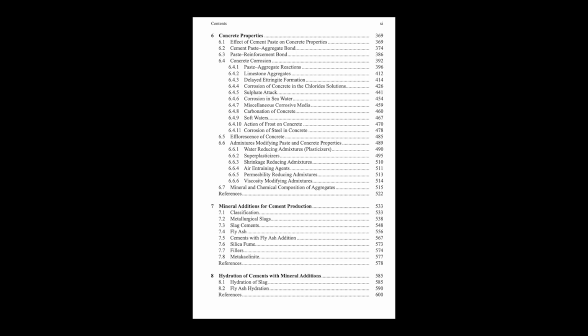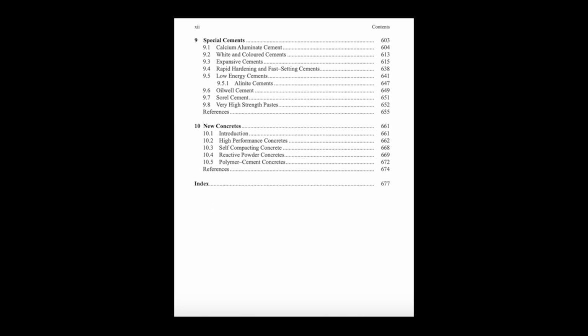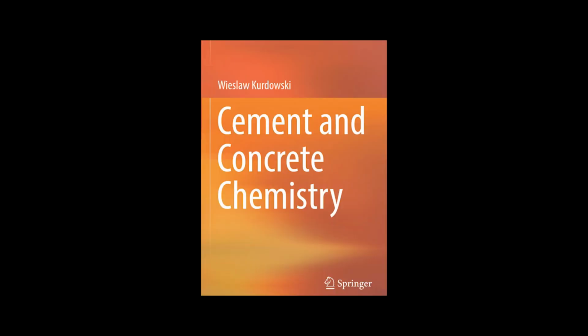Yes, the surface is chemically very active. It plays a crucial role in the paste's behavior. Nonat's model focuses on the acid-base equilibrium of silanol groups. Silicon bonded to hydroxyl groups. Right. On the surface, at lower calcium concentrations, these silanol groups can lose a proton, becoming negatively charged. And at higher calcium concentrations? Then surface siloxy groups, silicon bonded to oxygen, can complex with calcium ions from the solution, also releasing protons. So it's a dynamic surface interacting with the surrounding solution. Very much so. It affects how CSH interacts with water, ions, and other phases.